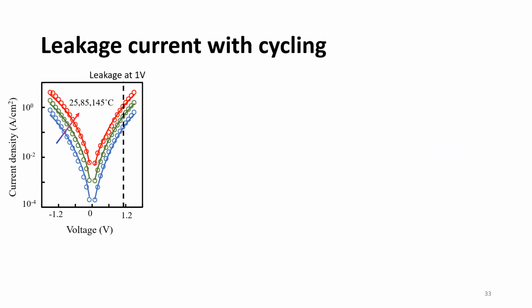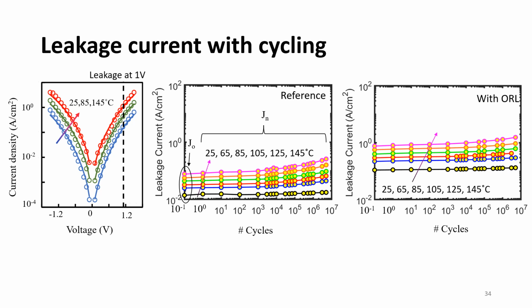Next, we wanted to find out the trap generation rate for both the devices. For that, we have plotted the leakage at 1 volt across different numbers of cycles for both the devices. The middle plot is coming from the reference device and the right plot is coming from the ORL device, which has tungsten oxide. Each plot has multiple curves which are coming from measurements done from 25 to 145 degrees Celsius. The leakage at pristine state, we will denote as J naught for the future studies that I will be showing, and the leakage after a couple of cycles, we will call Jn.